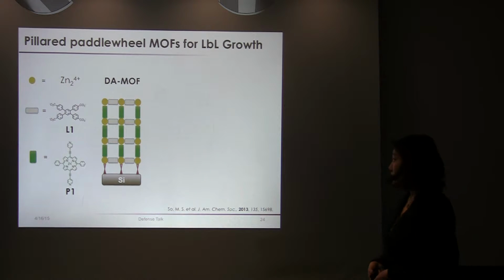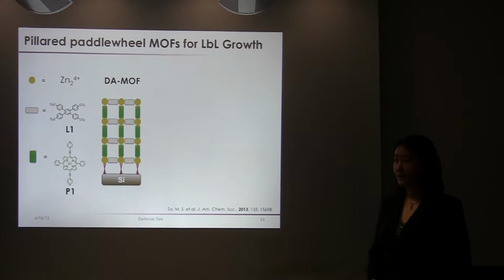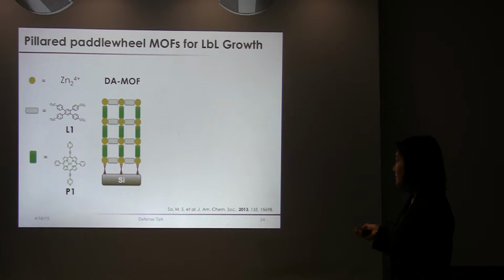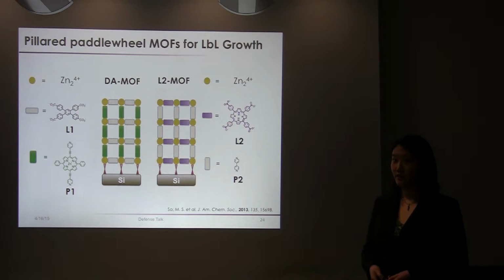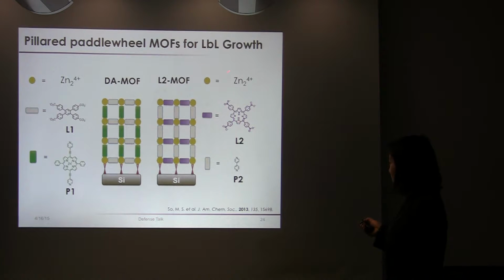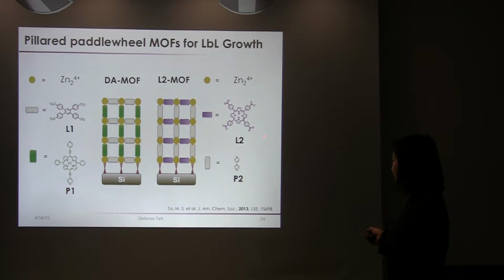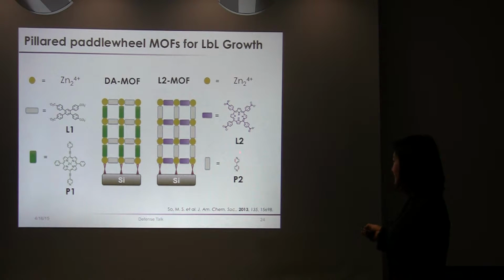So to do layer by layer growth, I used two different MOF candidates, one of which was DA MOF, because previously in our work, we had shown that there was very efficient exciton migration in this porphyrin-based MOF. And secondly, the second candidate I chose was the L2 MOF, which essentially includes the zinc 2+ ions, tetracarboxyphenylporphyrin, as well as a dipyridyl linker that acts as a spacer between the sheets of L2 porphyrin linkers. Let me note that the difference between these two MOFs is that the L2 linker, or the chromophoric linker in the L2 MOF, is in the XY direction, while the P1 linker in the DA MOF is oriented perpendicular to the substrate.